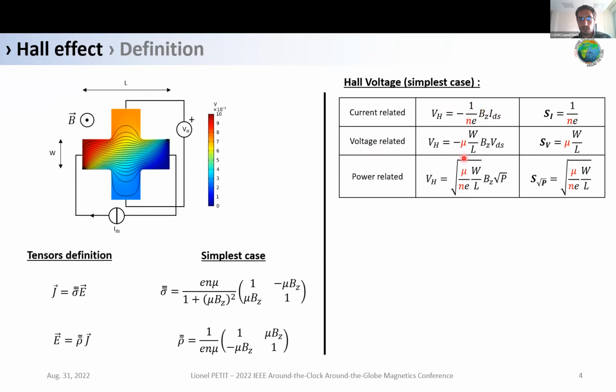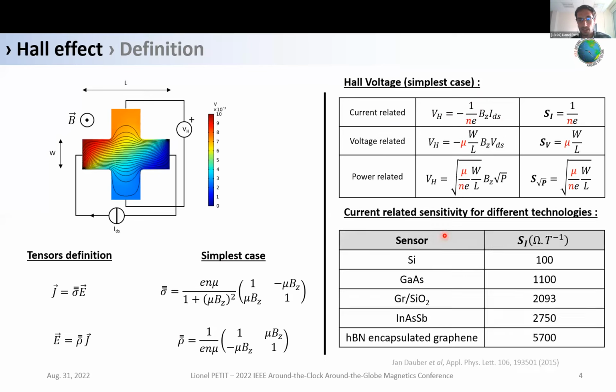And the link between everything is this normalized sensitivity. To increase this normalized sensitivity, we need to decrease n, which is the number of carriers, or increase mu, which is the carrier mobility. And that's why graphene is the best material for that. Here you can see a comparison between different technologies. And encapsulated graphene, I mean clean graphene, surpasses the best epitaxially grown heterojunction structure by a factor of 2 in terms of sensitivity.